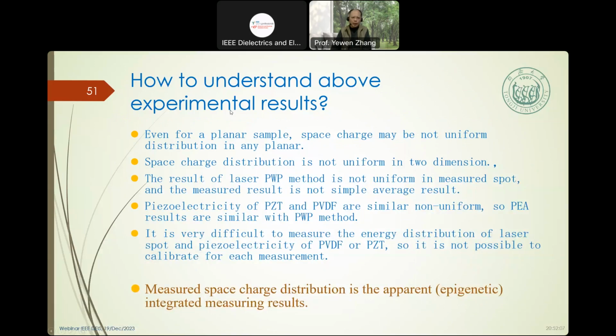How to understand the above experiment? Even for a planar sample, the space charge may be not uniform distribution in any planar. The space charge distribution is not uniform in two dimensions. The result of laser is not uniform in the measurement spot, and the measuring result is not the simple average result. The piezoelectricity of PZT and PVDF is similar, and is not uniform.